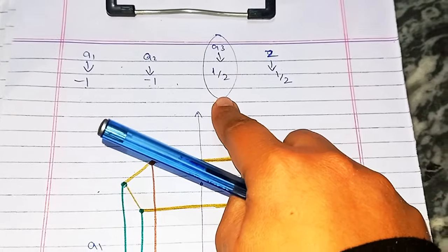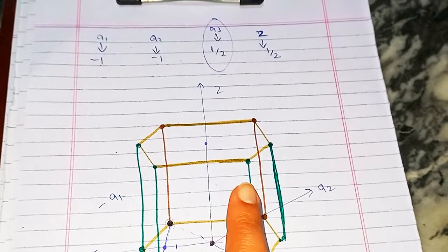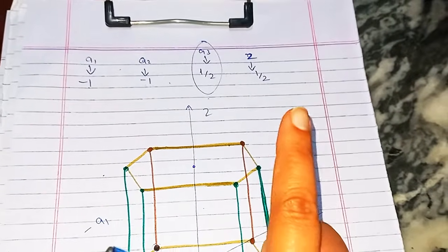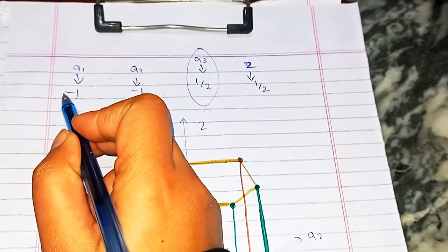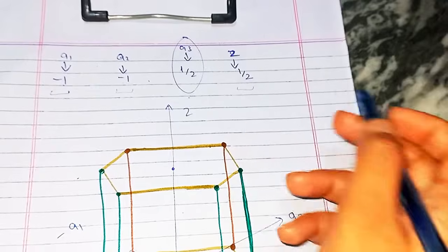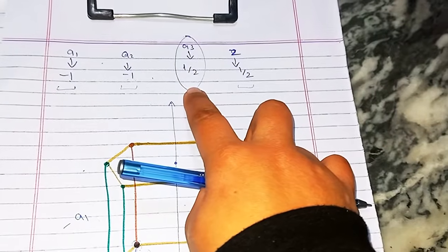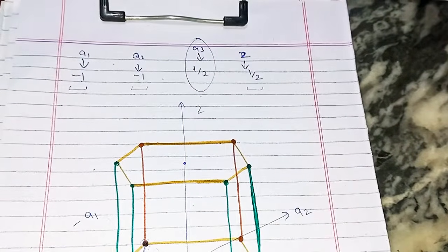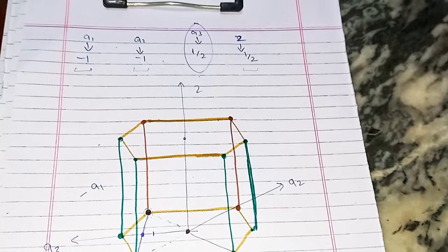When it's infinity, you have to keep it in the process. All right, keep that in mind, otherwise you'll get confused. So what I'm saying is that you only need the A1 intercept, A2 intercept, and Z intercept to draw the figure. You don't need the A3 intercept unless it's infinity. If it's infinity, you'll need that, as you saw in the first two examples.